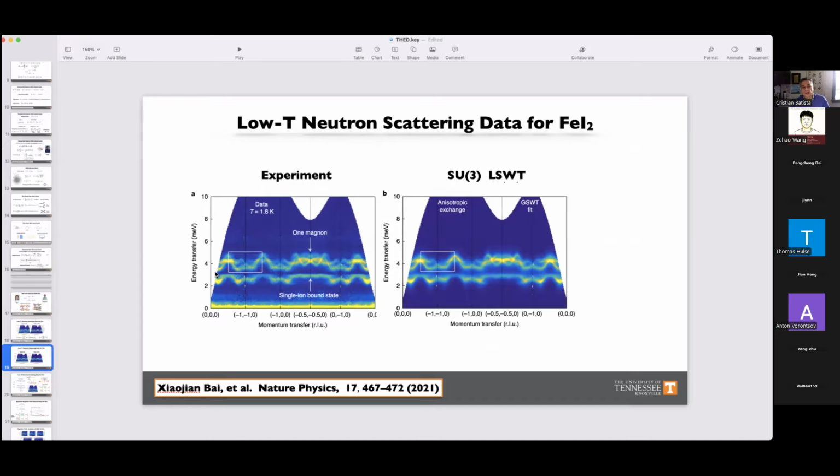Not only do you have magnons, or quantized spin waves that have some dispersion, but you also have a flat quadrupolar mode. When they hybridize, they open this gap. Now, this lower band is a hybridization between the quadrupolar and the dipolar mode. In the regions where you have less intensity, it has a stronger quadrupolar character. The regions with higher intensity have a stronger dipolar character.